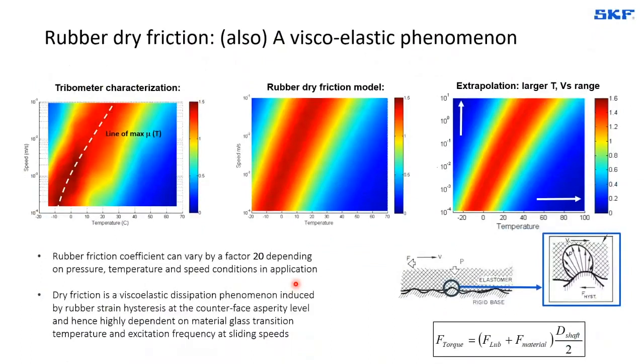Another, of course, important point to consider is the friction of the seal. I was talking at the beginning of this presentation about the highest demand on the lower friction for our application. And here, a parameter that is crucial to be considered is, of course, the dry rubber friction, or the dry polymer friction, if we talk, for example, about polyurethane seals. What is important is to understand that there's no such thing as a friction coefficient per se. The dry friction of rubber is a very varying parameter that is extremely influenced by speed, as can be seen here, but also by temperature and, of course, by normal load.